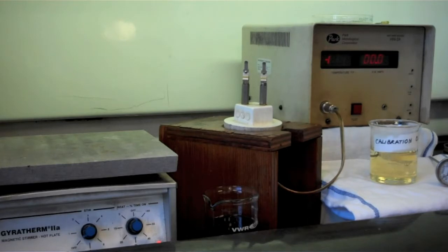In the hot wire testing, the wire is heated from room temperature to a higher temperature by passing an increasing electric current through it. The heat generated in the wire is continuously taken away by the oil until a point is reached when the generated heat is more than that's taken away by the oil. At that point, the wire fuses, and that's what we call the hot wire reading.